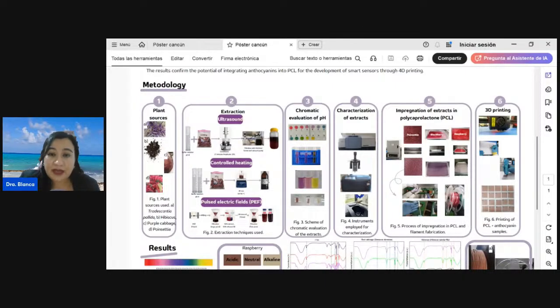After extraction, stage 3 was the evaluation of the color change, modifying the pH of the solution and showing this color change in every extract. In stage 4, we characterize the extracts with Fourier transform infrared spectroscopy or FTIR, and we use UV visible spectroscopy, and we evaluate the color change.